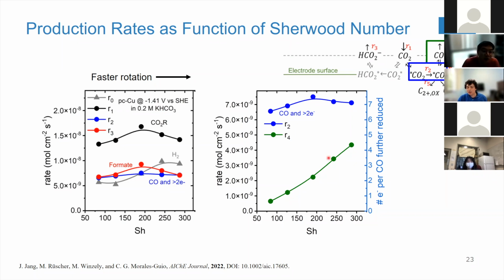And from here, you can also calculate the conversion. At low Sherwood numbers, the conversion of CO is quite high because not a lot of CO escapes, and we see a lot of different products that are made from CO. And as you go to high Sherwood numbers, you see more carbon monoxide and less of the further reduced product.